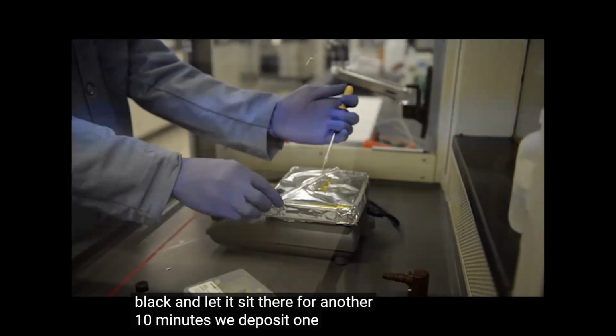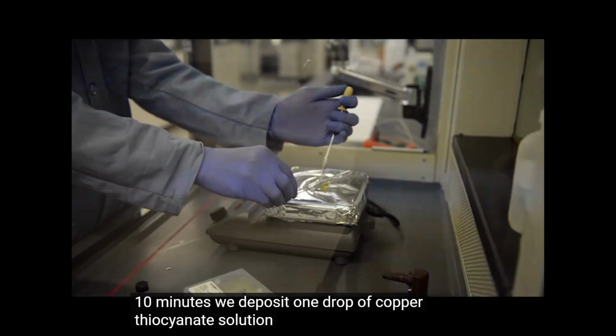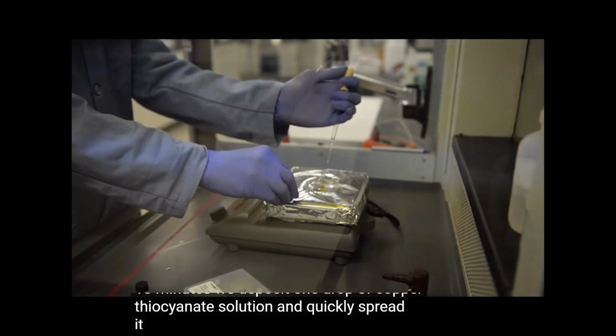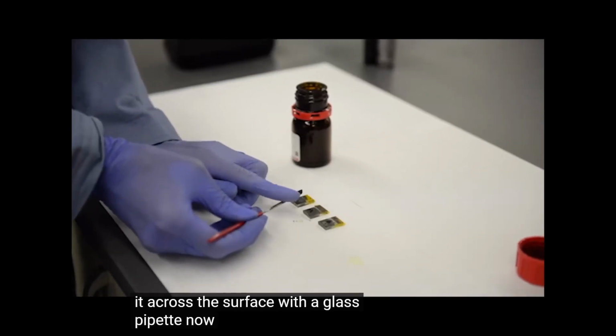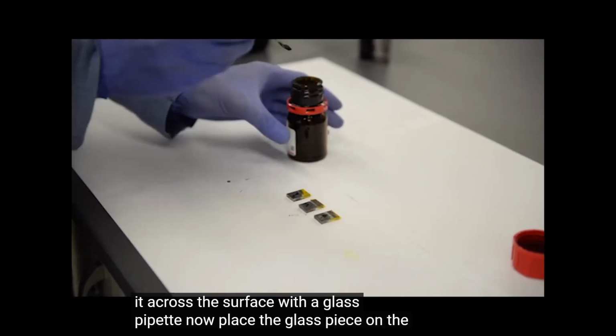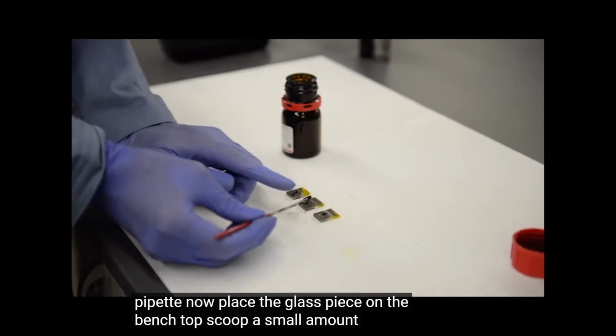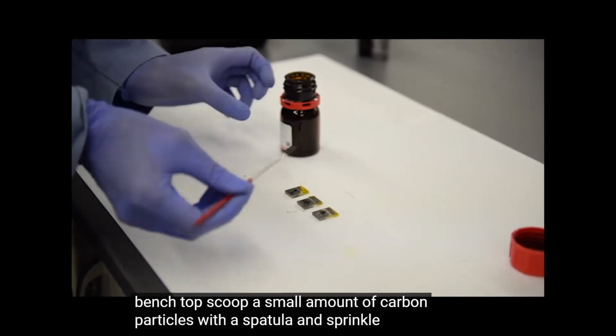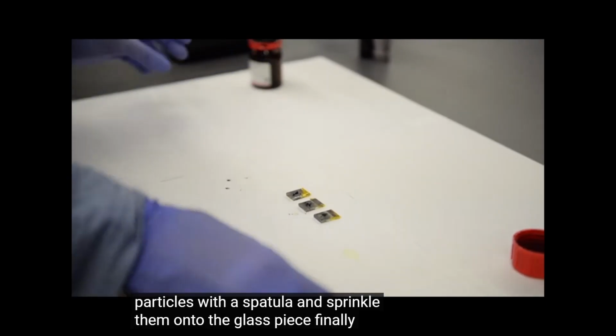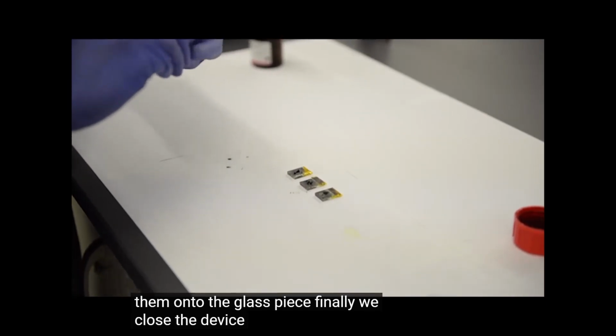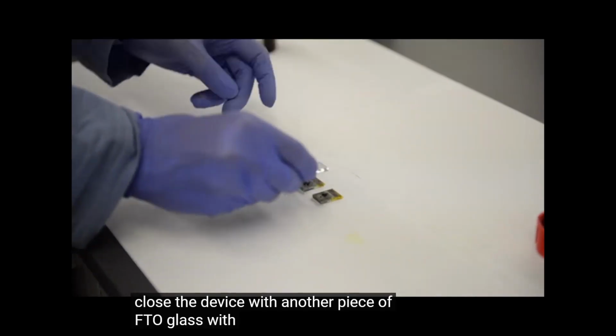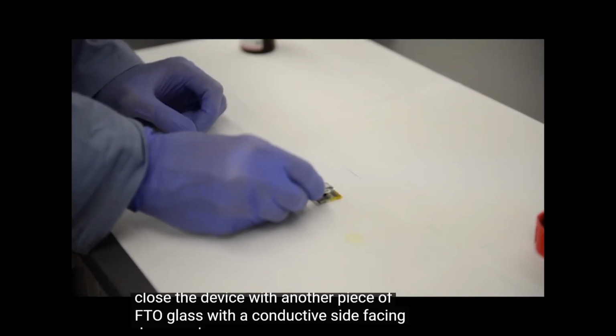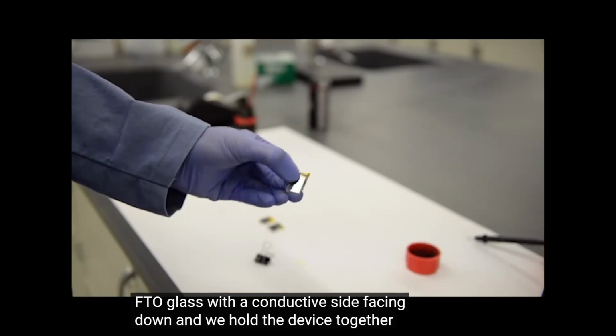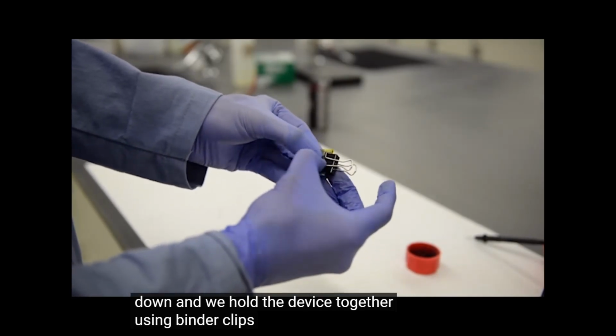We deposit one drop of copper thiocyanate solution and quickly spread it across the surface with a glass pipette. Now place the glass piece on the benchtop, scoop a small amount of carbon particles with a spatula and sprinkle them onto the glass piece. Finally, we close the device with another piece of FTO glass with the conductive side facing down, and we hold the device together using binder clips.